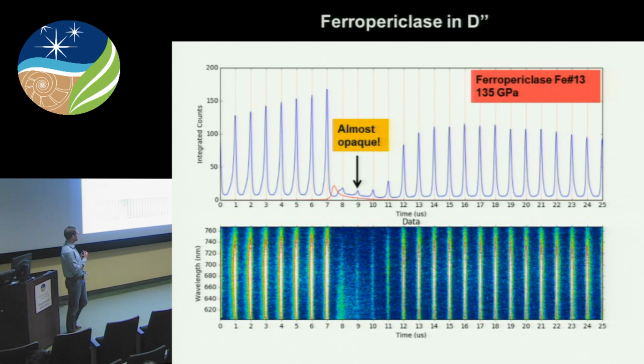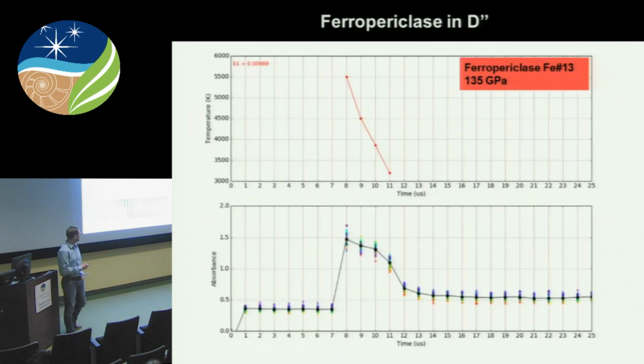And this is another example. This is ferropericlase in D double prime at 135 GPa. You can see that you barely have thermal background coming from your sample, but you do have a lot of absorption at around this time. So when the sample is hot, it essentially is very dark. This instantly tells us that